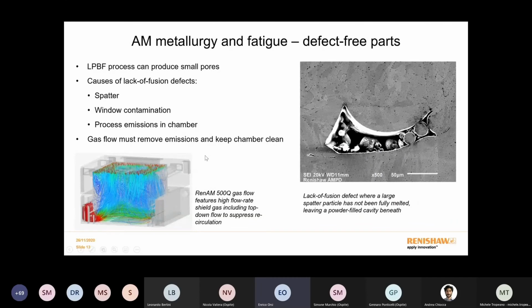Another type of defect is related to emissions from the melt pool that can create defects like this one. You see here you have about 50 micron dimensions, so this defect is about 150 micron across. If you think about the process, and this is the horizontal plane, this defect is generated by a spatter part in this area that has covered the plate, and it has generated a cavity underneath and did not allow the laser energy to reach the powder properly. That is then left unmelted. So you have all sorts of different defects that arise from the process if it's not adjusted properly.